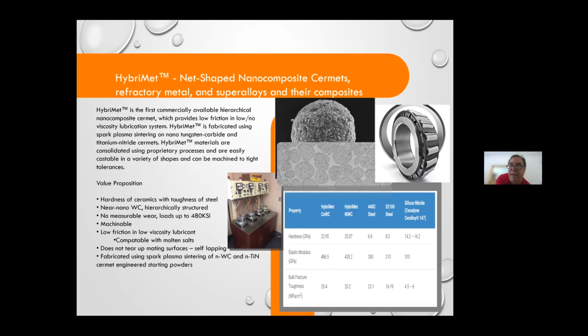We offer this in both a consolidated version and as a coating for structures. And by tailoring that matrix, we have versions that are compatible with molten salts at up to 800 centigrade, with supercritical CO2, and with very poorly lubricating environments, such as basically using water as a lubricant to get reduced friction and frictional losses. Because of the nanostructures, these form a hydrodynamic film, even with a 1 centipoise salt water, so that they are basically lubricating and very low wear and very low friction with any kind of simple lubricant around.